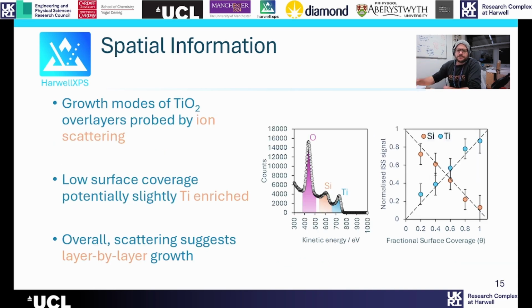So the final thing that we wanted to look at was the spatial location of our deposited films, and they should all be on the surface, and there are ways that we can use XPS to probe this, as well as complementary techniques such as ion scattering spectroscopy. Now, ion scattering spectroscopy indicated that the surface coverage increased in an approximately linear trend, as we would expect for this synthesis. So our reaction is self-limiting in nature, and it should be incapable of forming larger island type structures, provided that our synthesis is kept completely anhydrous and free from moisture.